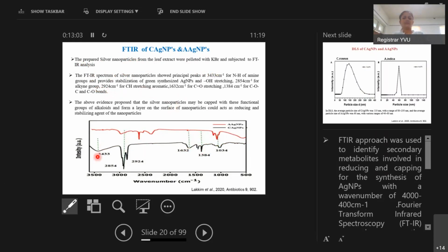The principal peaks are 3433 per centimeter for amino group stretching, which provides stabilization of the green synthesized silver nanoparticles, 2854 for the alkyne group, 2924 for CH stretching and aromatic ring stretching, 1632 for C=O stretching, and 1384 for C-O-C and carboxyl and C-O bonds. The above evidence suggests that the silver nanoparticles may be capped with these functional groups, forming a layer on the surface of the nanoparticles that could act as reducing and stabilizing agents.